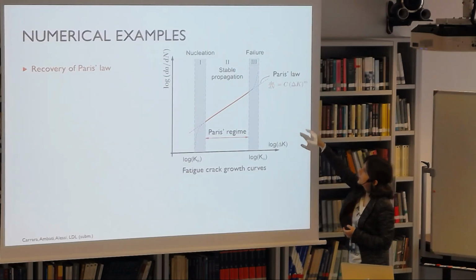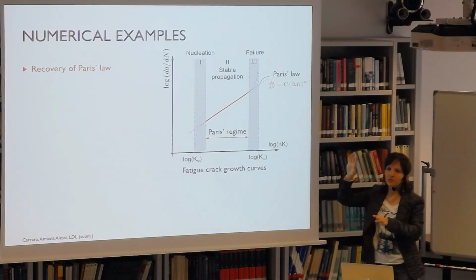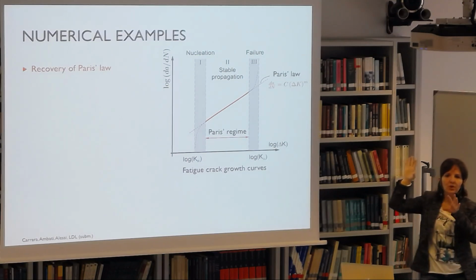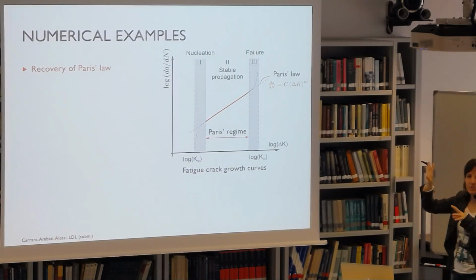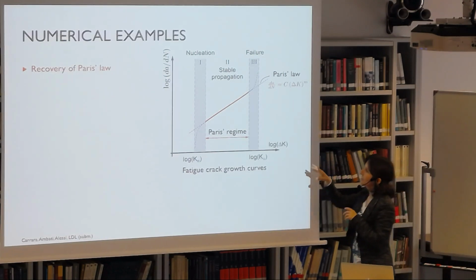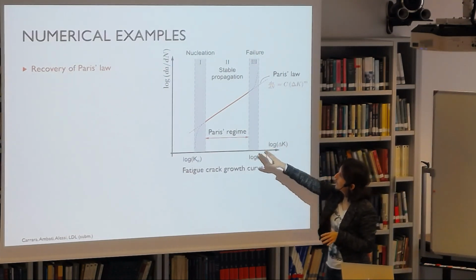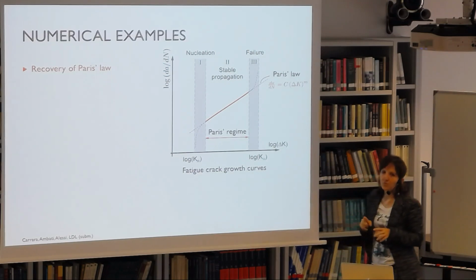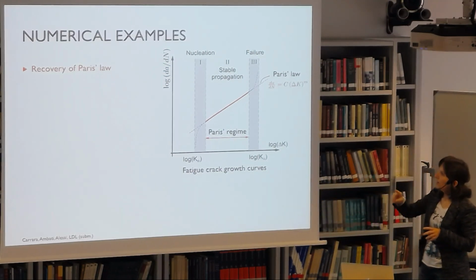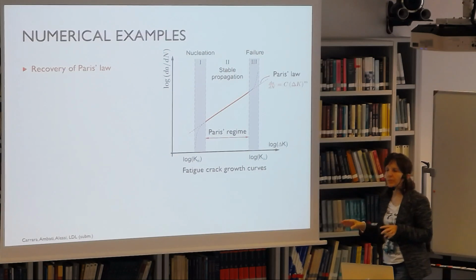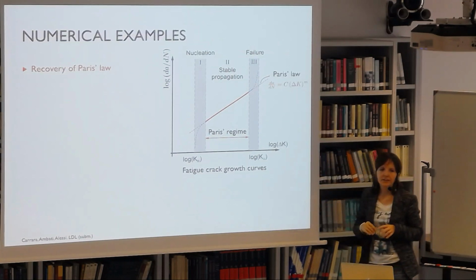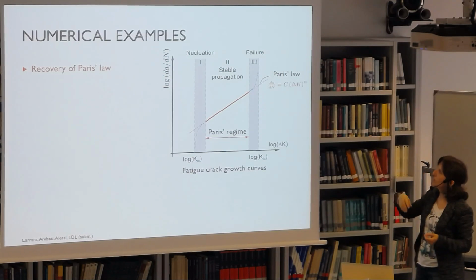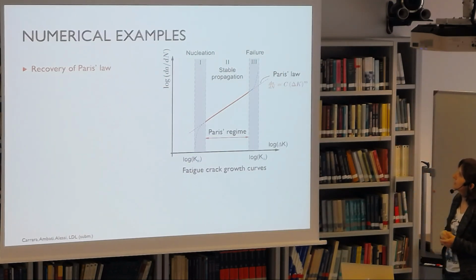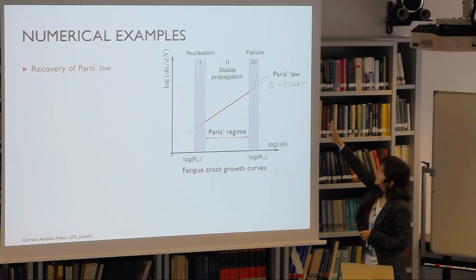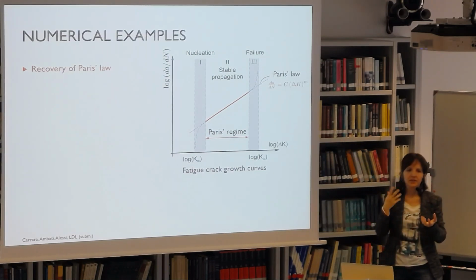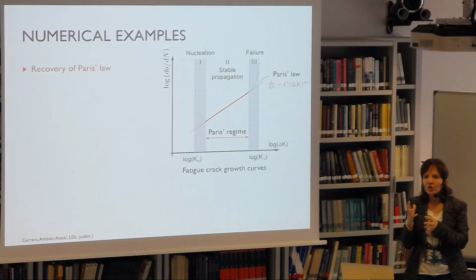there is a final phase that corresponds to failure, and on these phases there is not so much to be said because these are both case-dependent, geometry-dependent, and so you cannot say anything general on those phases. But in the middle, there is a stable crack propagation phase, which obeys in the log-log plane a fairly linear law, which is known as Paris law. So dA/dN is basically given by C times delta K to the power m, where C and m are two parameters that are only material dependent.